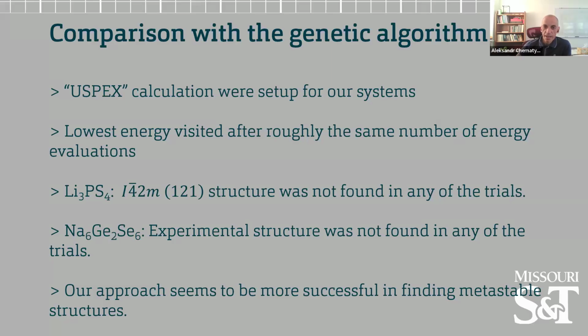The important difference that we found is that the USPEX calculation, not being restricted to a particular space group in the first place, typically finds the lowest energy structure and then hangs around that lowest energy structure and has a little bit of difficulty finding various metastable structures. That comparison is not entirely fair because we are not experts in genetic algorithm methods, and it is entirely possible that you can tweak the algorithm so that it would look for the metastable states. But nevertheless, we see that we can fairly confidently find metastable structures in addition to the stable ones, which I think would be the key to look at the various disorder states. And so this is sort of a key result of the comparison here.